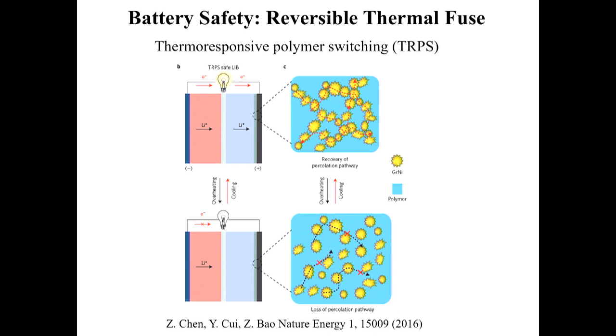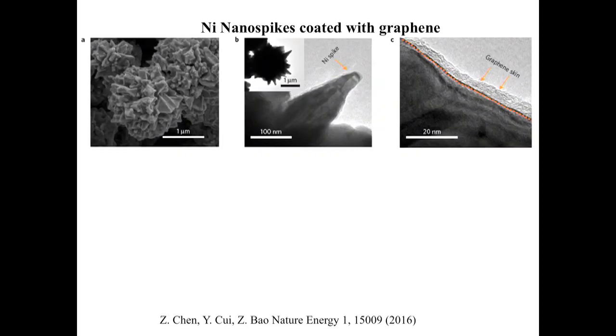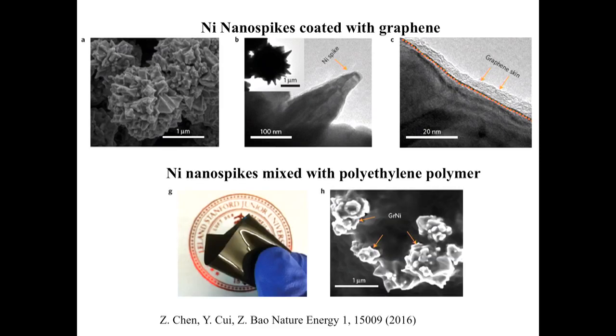Once you have expansion happening due to thermal heating, it will pull these particles apart, right? It becomes an insulator. If it becomes insulating, you have shorting right there. This metallic foil is not connected with this particle or battery material. The electrons have a very hard time leaking into the metallic foil and passing through the short. So you don't have a big current passing through your battery, so you don't heat it up that much. So we build these nickel nanospikes and make them stable with a layer of graphene, forming this flexible layer.